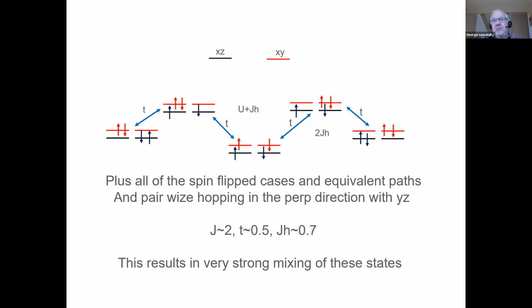Nobody actually knows, because of the STO materials. The STO that is used, and that was this double layer I was talking about. In order to get rid of the oxygen vacancies as much as possible, they heat it up to around 900 degrees Kelvin in oxygen. And that removes the oxygen vacancies. But what it also does is it removes some strontium from the first layer. And you then get an STO which is basically almost pure, with a double TiO2 layer. But it doesn't have the same structure as the terminating TiO2 layer of STO. It has a complicated structure. These are the beautiful results of the surface X-ray truncation rod experiments by Clejou and who was it?